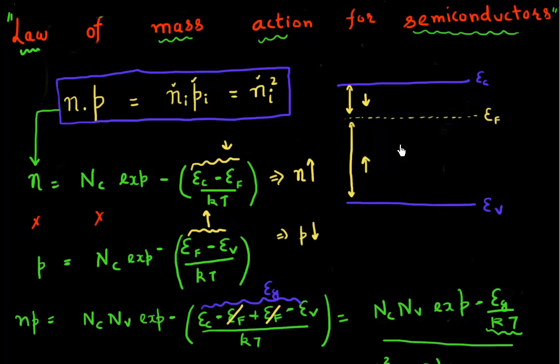Similarly, instead of moving that Fermi level from mid-gap to the conduction band, I could move it close to my valence band as well. In that case, I'll have a small Ef minus Ev. But I'll have a large Ec minus Ef. So if I put that again in this formula, what I'll see is that the number of electrons would decrease exponentially, and my number of holes would increase exponentially. So this is another way to derive that same formula.